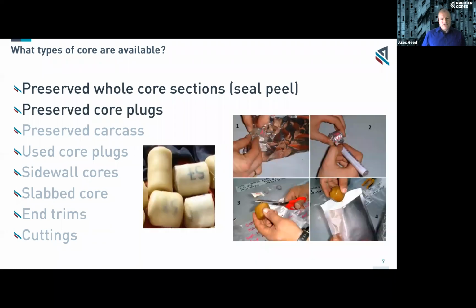We also then have preserved core plugs, and basically the process is exactly the same. We might wrap the sample in a plastic film first, a sort of oil-resistant plastic film, then aluminium foil, and then into a wax dipping to again seal the sample off from the atmosphere and preserve the contents of that sample.